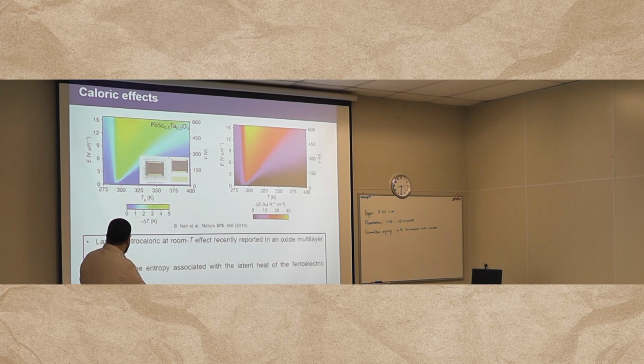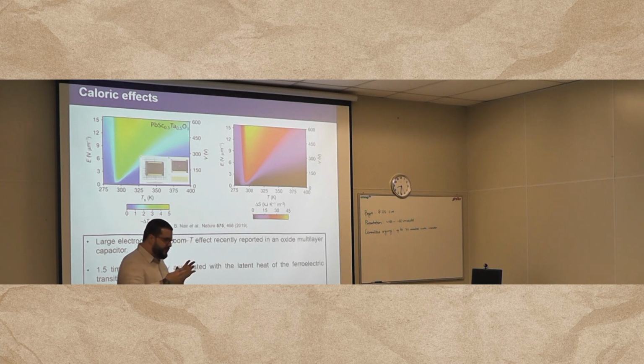And not only that, but they have accessed 1.5 times the entropy associated with the latent heat of the ferroelectric transition. So they tuned this transition to a supercritical regime where they have enhanced the entropy even more, and this large caloric effect was a result of that. And our proposal explains this large electrocaloric effect because it has a lot of entropy contributions: this is a ferroelectric system, so it has dipolar configurations, it has the multilayer capacitor or the Maxwell-Wagner contribution associated with interfaces, and we were able to explain these large electrocaloric effects in terms of our proposal.